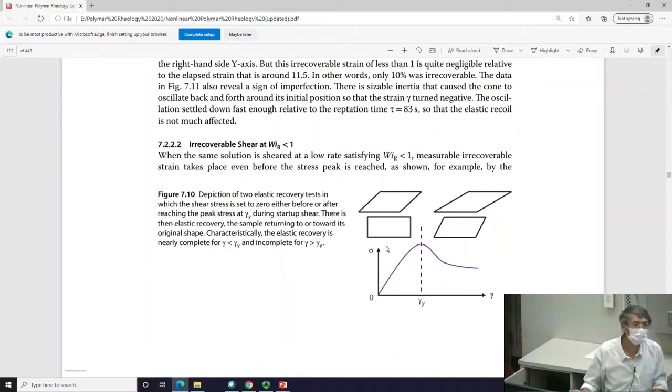For that reason, this point is sufficiently persuasive that at least some overall structure retains sufficient integrity that upon unloading, meaning upon releasing the force you apply to it, it can snap back and elastically recoil completely. Whereas after the maximum, it cannot. So this point, I think, should be very uncontroversial, okay? But that's all I can offer you. That's the meaning of it.